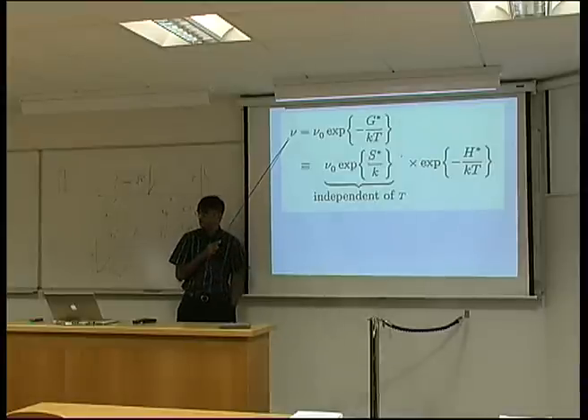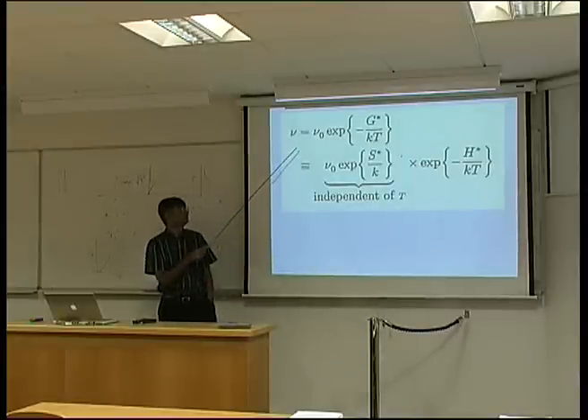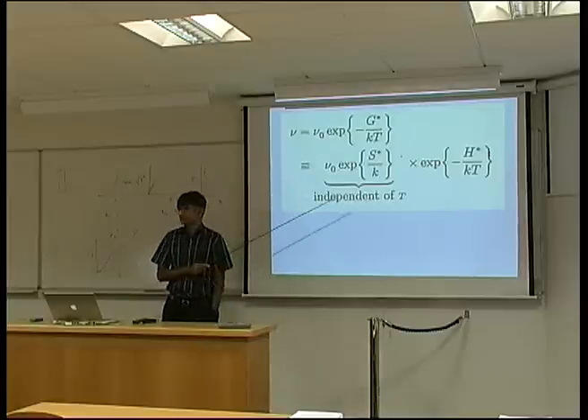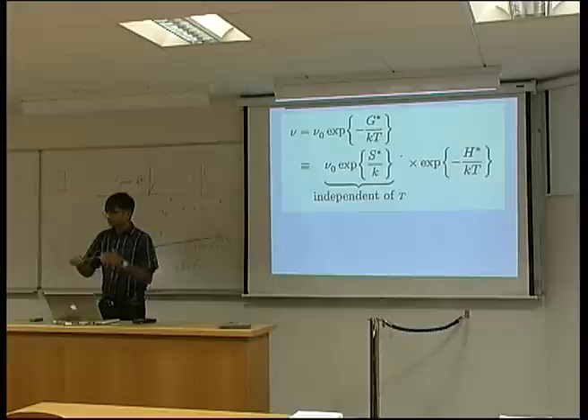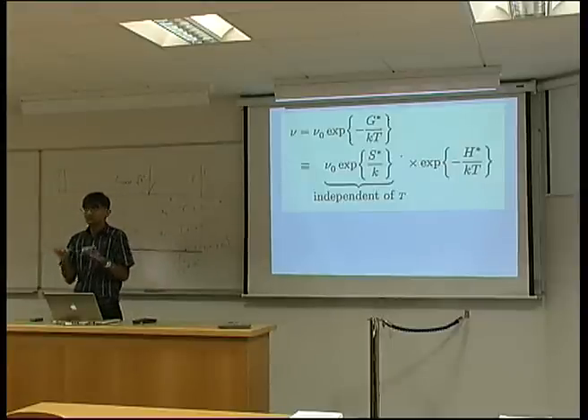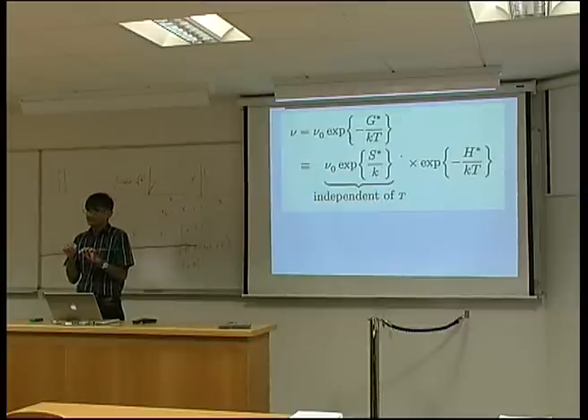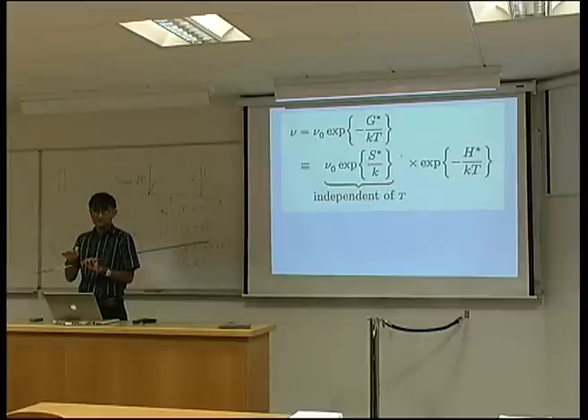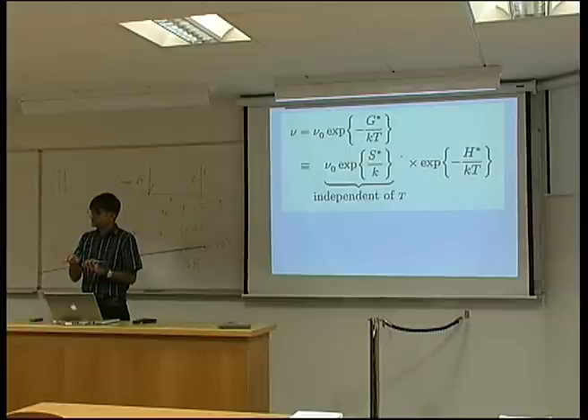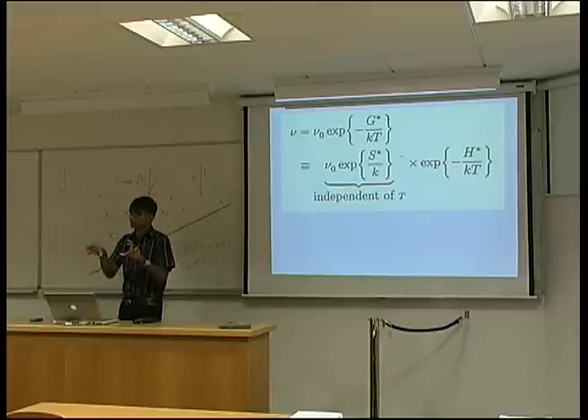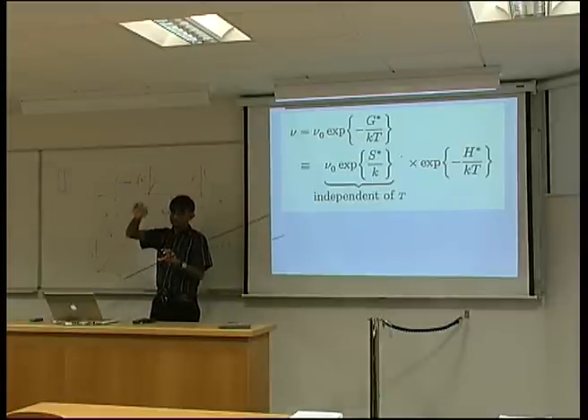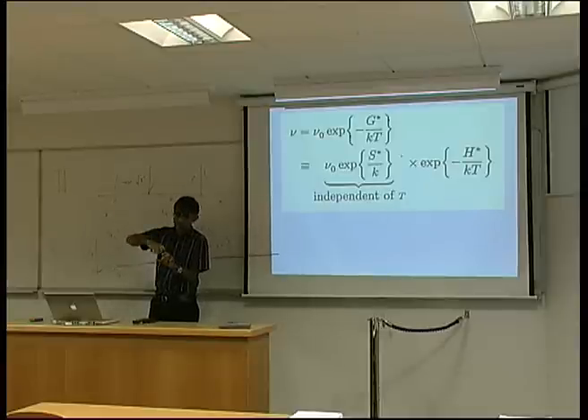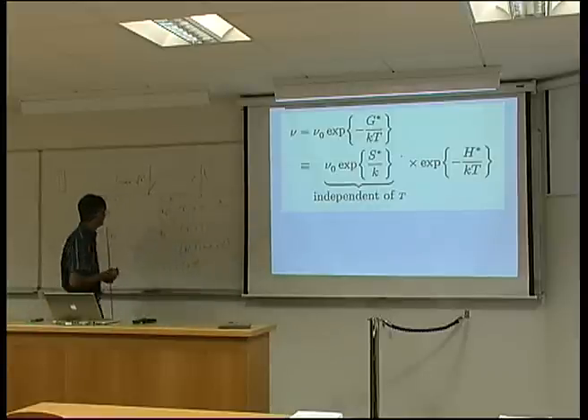we can expand that term we had, which was the jump frequency, into a fundamental jump frequency, which is like the Debye frequency. All the atoms are vibrating at a certain frequency, let's say 10 to the 13 times per second. Now, of course, that doesn't mean that the atom actually jumps 10 to the 13 times. It means that it attempts a jump 10 to the 13 times per second, right? Whether or not that jump is successful depends on the barrier across which it jumps. Because to move from one equilibrium position to another, there will be some kind of an obstacle. It'll have to push past other atoms. So that's what we call an activation barrier.